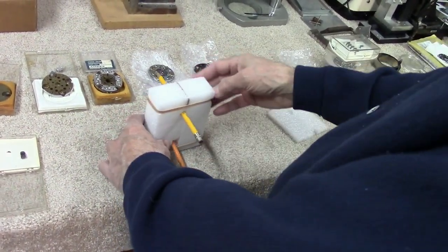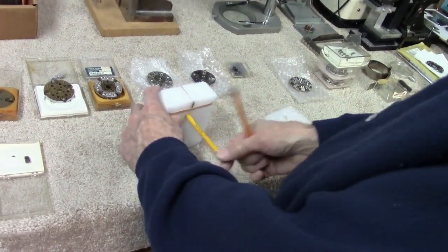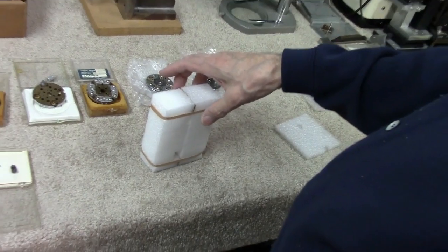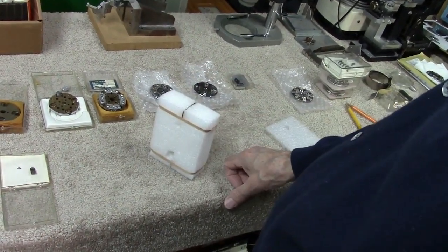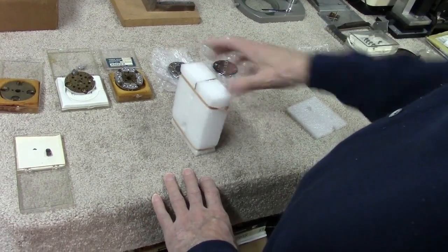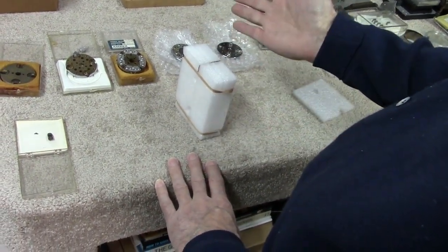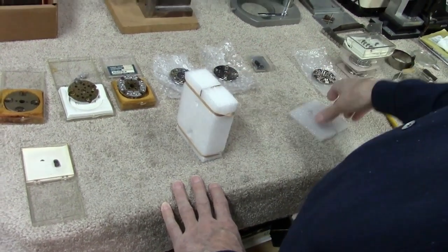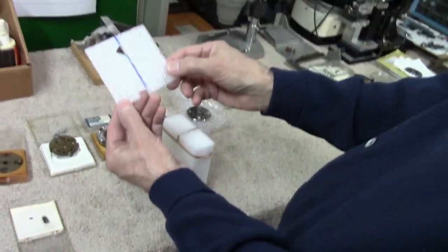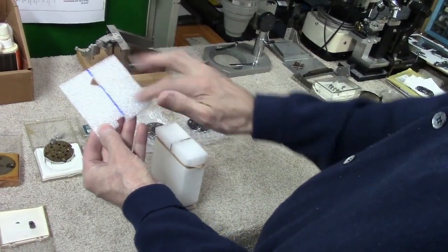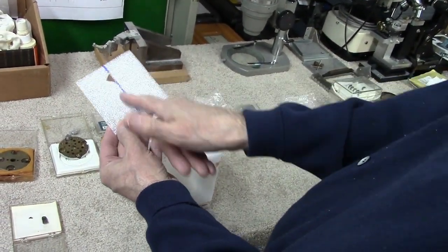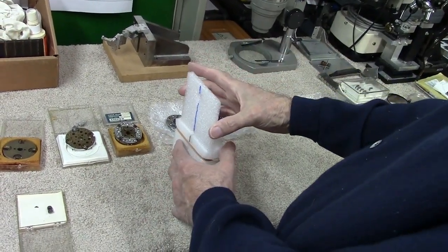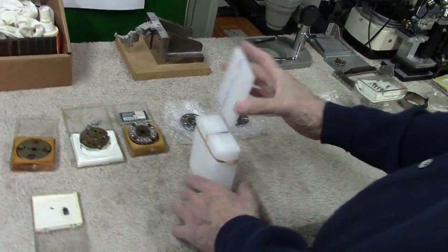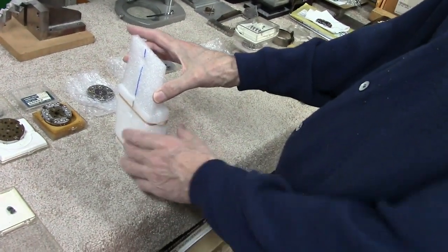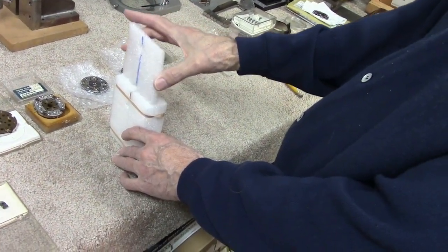Okay, everything went well, and you take it out of the oven. And now you have a bonded block. From this, we would slice our tip cores. So this would be our tip core with our two halves and then the glass bonded gap. And so from this one block, we would slice several tip cores.